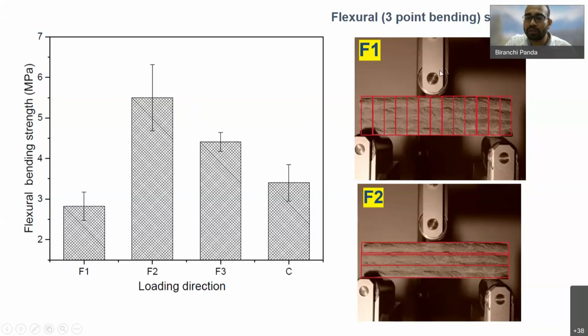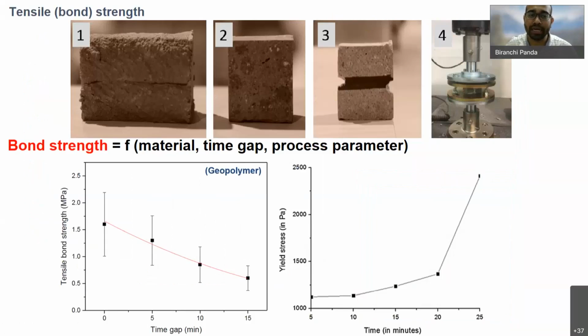And when we discuss the poor bending performance in the F1 direction, we found that an interesting phenomenon happens, which is the bond strength. If the bond strength can be improved, the strength in the F1 direction can be improved. Then we started investigating the bond strength, and for that reason we printed 2 layers of concrete with different time intervals, because as we know the concrete hardens with time. With different time intervals we printed these 2 layers and did the bond test, and we found that this bond strength is a function of material, time gap and process parameter.